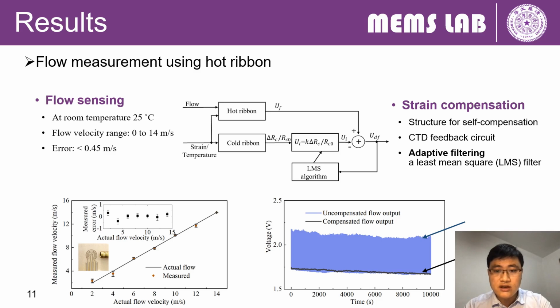To solve the strain effect on flow sensing, we propose a hybrid compensation method, including concentric annular design and a CTD feedback circuit. However, residual strain induced artifact still exists in flow sensing output, as shown in the blue curve. Here, we propose a digital adaptive filter using least mean square filtering technique to solve this issue and realize perfect strain compensation as shown in the black curve.